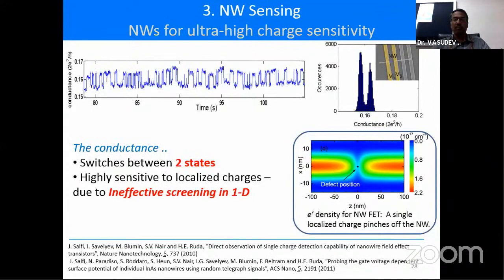Now, the data I'm going to be talking about will be for indium arsenide nanowires, and those nanowires have surface states, or donor-like surface states, which are resonant with the conduction band and are generally occupied to form a two-dimensional electron gas. And in fact, very early on, a lot of the power amplifiers, FETs and so forth for microwave type communication were based on using this two-dimensional electron gas. Here in the case of nanowires, the surface states themselves can be occupied either directly or through border state type occupation.